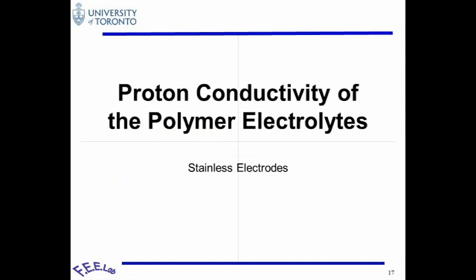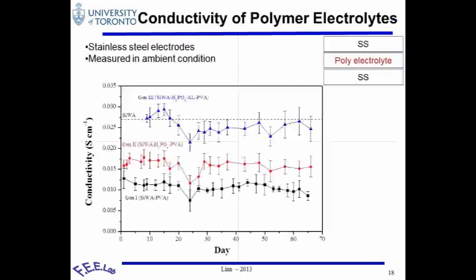So let's first look at this polymer film that we've developed in terms of their conductivity. We're based on this material, sandwiched in between thin film, 2 mil thick stainless steel. And these are three types of conductivity that we have monitored over time, about a 2-month time period.